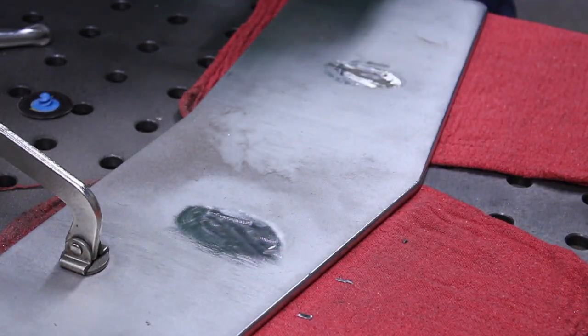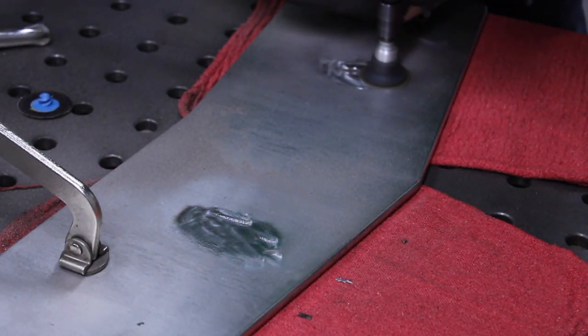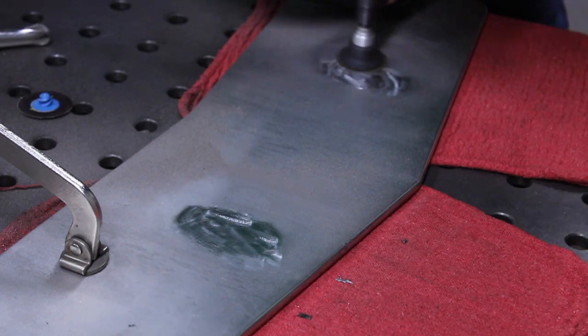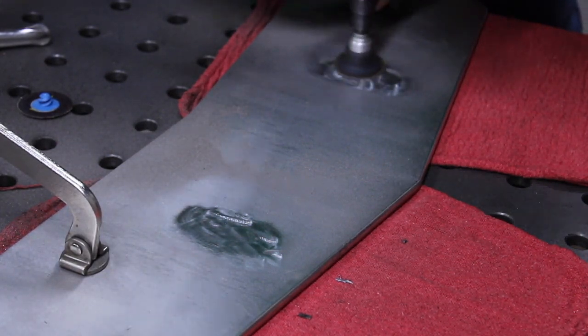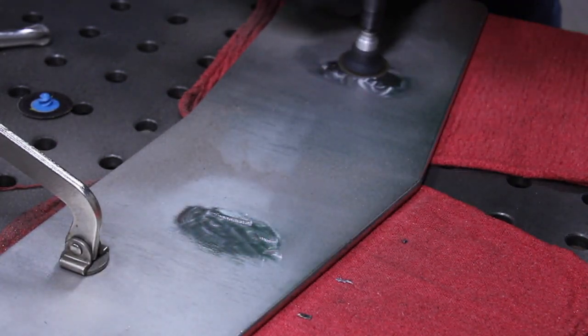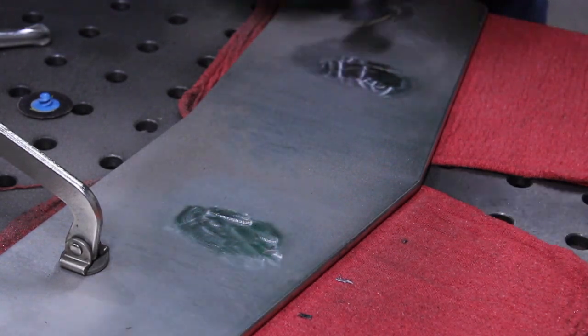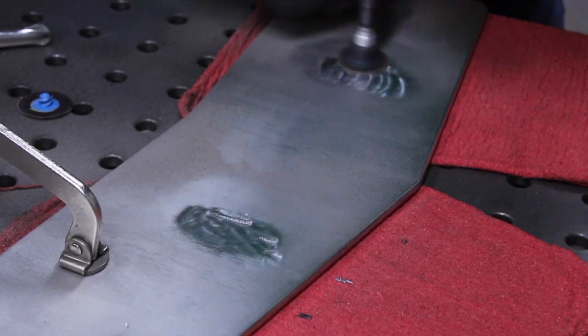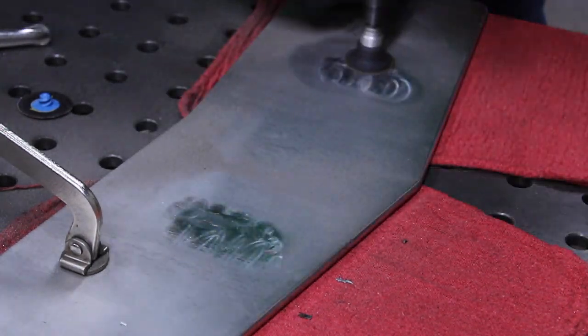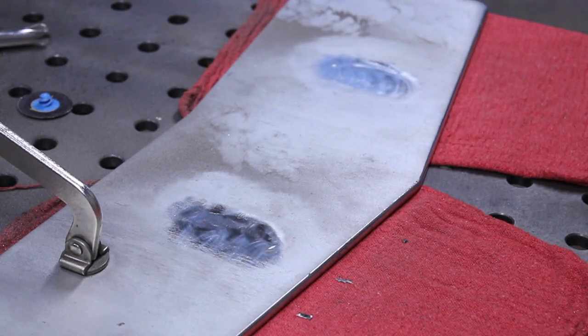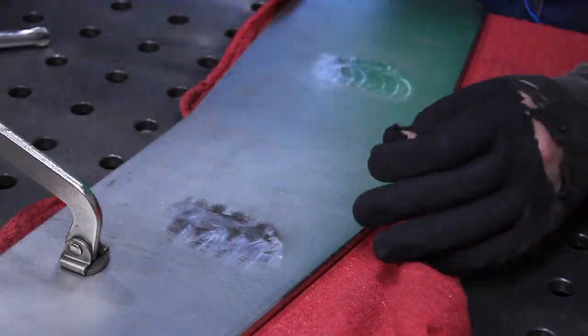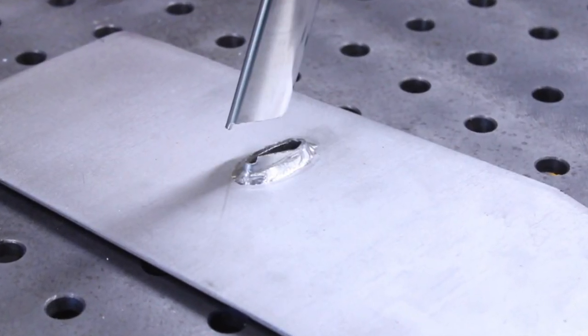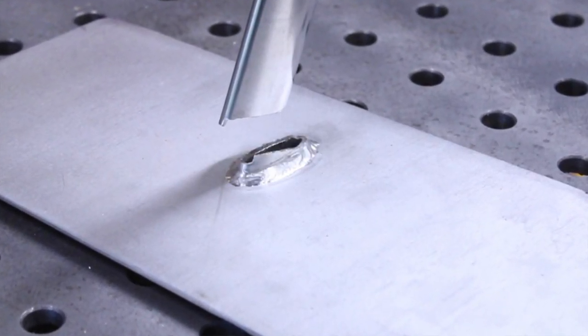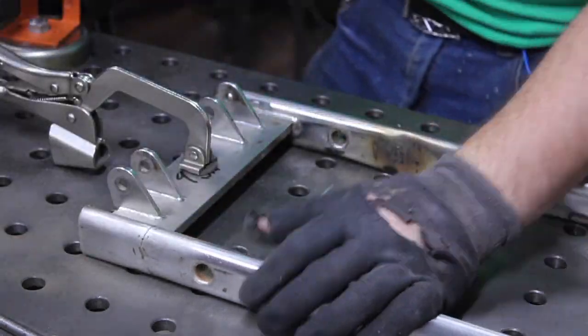And the reason for that is you have two parts here. One, the plate underneath, is 3/8 of an inch thick, and the tubing wall thickness is roughly 1/8 of an inch, a little under that because it's metric. And so you have some pretty big size differentials going here. One part is going to be overheated. This part broke at the ending heat affected zone of that pipe up there, if you go back and look. And we're trying to mitigate that.